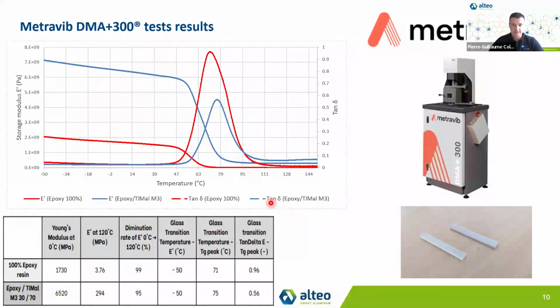So the tests that have been conducted with the partnership with Metravib are based on epoxy 2K room temperature system. So we have decided to highlight some differences. So the first is only pure epoxy in red on the chart. And the other one is epoxy filled with our TIMal M3 ready to use multimodal ATH. So we have achieved 70% by volume filler content, which is pretty high, as we wanted to show some differences and also to highlight the performances in terms of thermal conductivity that could be achieved. So we will see after that.